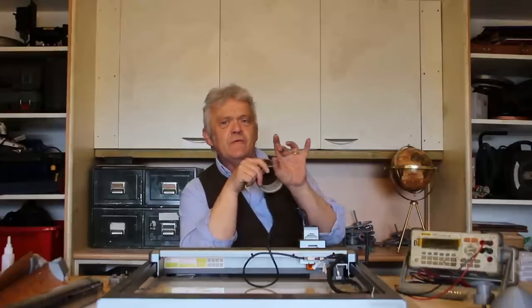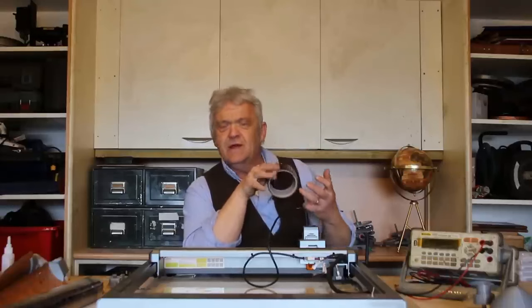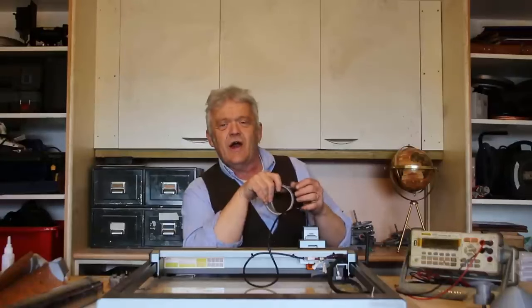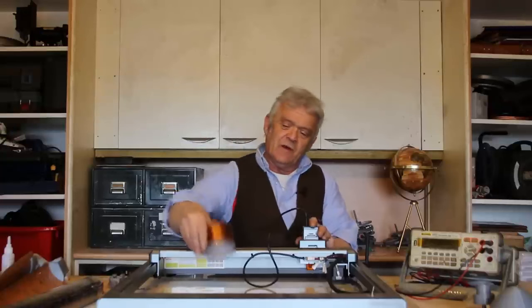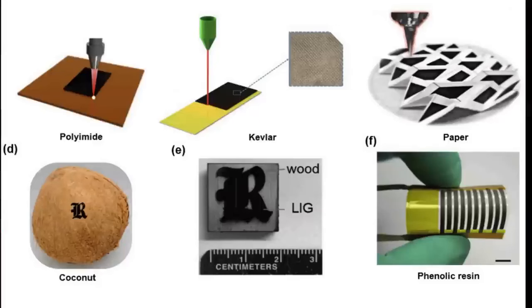If you defocus the light, then every time you move a spot, you are effectively multi-lasing an area and you get a needle-like growth by defocusing the light. Now, when they discovered that Kapton worked quite well, of course, they went on to other things. And now they've discovered that you can actually scribe graphene onto a whole host of things, including paper, wood, a